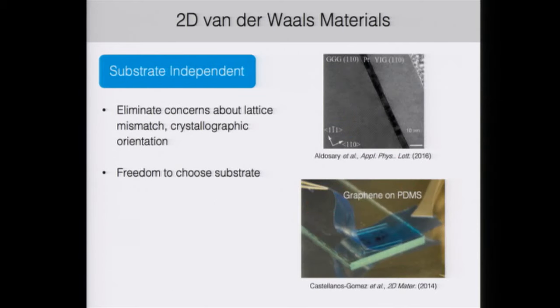Van der Waals materials are also substrate independent. If you want to perform epitaxial growth, you have to think about your underlying substrate and the crystallographic orientation, and there can be concerns about lattice mismatch that introduce strain at the interface. Whereas with van der Waals materials, we really have the freedom to choose whatever substrate we want. Here is graphene on a flexible PDMS substrate. We really can pick these layers up and place them as we please on whatever final substrate target.